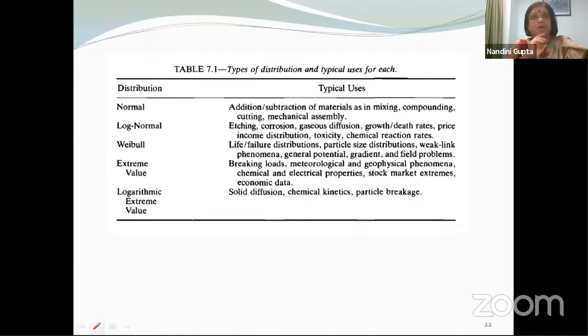For example, when we are talking about the movement of gas molecules in a heated or unheated condition before breakdown, that can be very nicely defined or described using a normal distribution. But then we have the log normal distribution. Log normal distributions are generally used for gaseous diffusion or chemical reaction rates. What we are interested in dielectrics are Weibull distributions, because Weibull distributions are the distributions to which the life data or failure data best approximate. Particle size distributions, so any kind of weak-link phenomena.